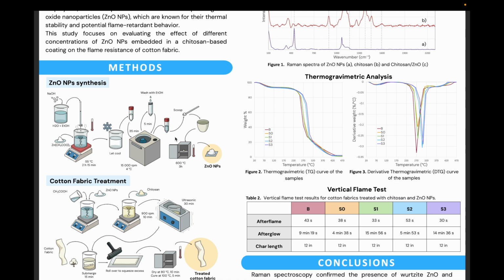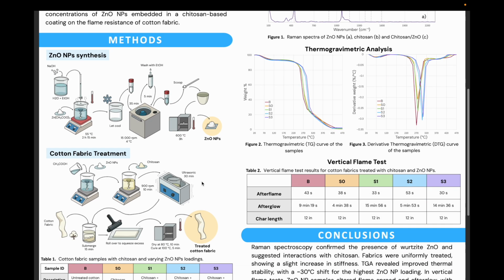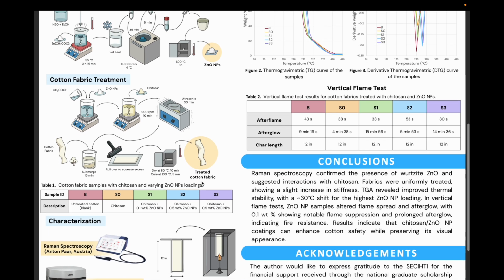The precipitate was washed with ethanol and centrifuged again for 5 minutes. Finally, the precipitate was collected and calcined at 600 degrees Celsius for 3 hours. In this way, zinc oxide nanoparticles were obtained as a white powder. Next, the cotton fabrics were treated. The desired amount of zinc oxide nanoparticles was stirred with a 1% acetic acid solution.